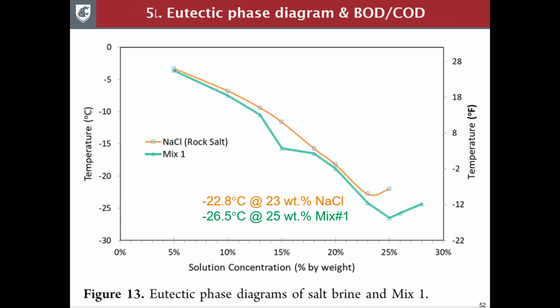We also look at the eutectic phase diagram. The orange one is the traditional sodium chloride or rock salt, and the mix 1 gives us basically a lower eutectic temperature at 25% as its eutectic concentration.